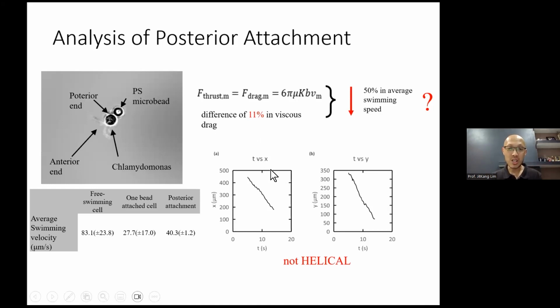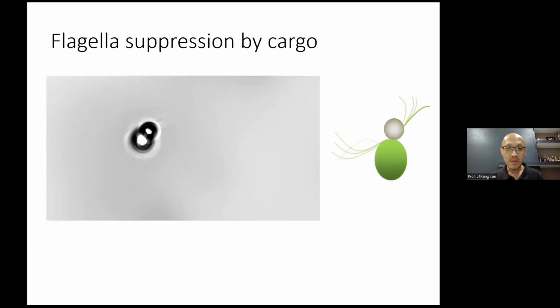But one thing we notice is, if we look at the motion path of this construct again, we didn't see any helical motion. After it picked up the beads, it still moved quite translationally. And that's important. Once we rule out the mass addition, it's not the reason. We rule out the geometric contribution. It's not. The only one left is a very sensible one, which, as suggested by another group as well, is that the presence of the microbeads on the stroking path of the flagella can actually obstruct its motion, and this hinders the microbot from doing work.